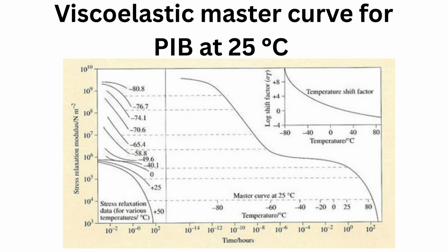As the material passes through the transition region, the modulus drops rapidly. The material is becoming rubbery in its response to the applied stress. The onset of true elastomeric behavior is marked by the so-called rubbery plateau. This is followed by another steep fall in modulus, where viscous flow occurs as the temperature is raised further.